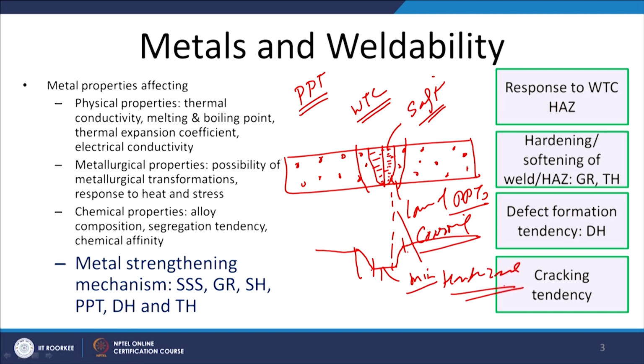So if we see in this case, the failure fracture will occur from the weld metal, while in other cases where the HAZ is weaker, then the fracture will occur from the heat affected zone. So it is the minimum hardness zone that will lead to the development of the fracture under external loading or during the tensile test.